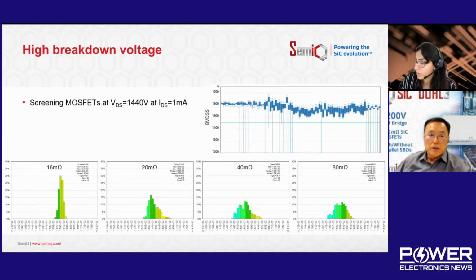So we have two steps. The first step is we test at room temperature, industrial grade. We measure the reverse leakage at 1 milliampere and apply the negative bias. Any device which has a VDS less than 1440 or 1450, we screen out. Even though our device spec is 1200 volt, with screening, it's not avalanche conditions, but at least at 1 milliampere leakage level, we're checking the reverse voltage. That's called the high voltage reverse bias testing.